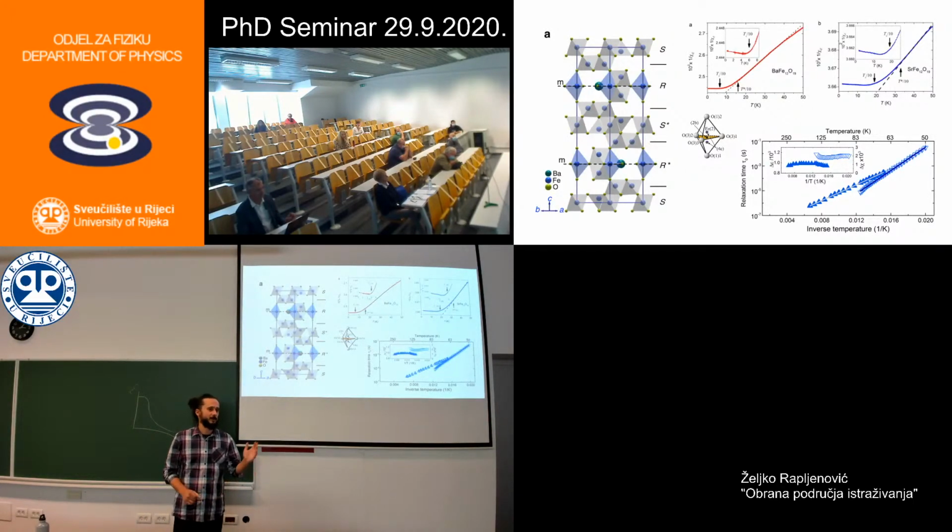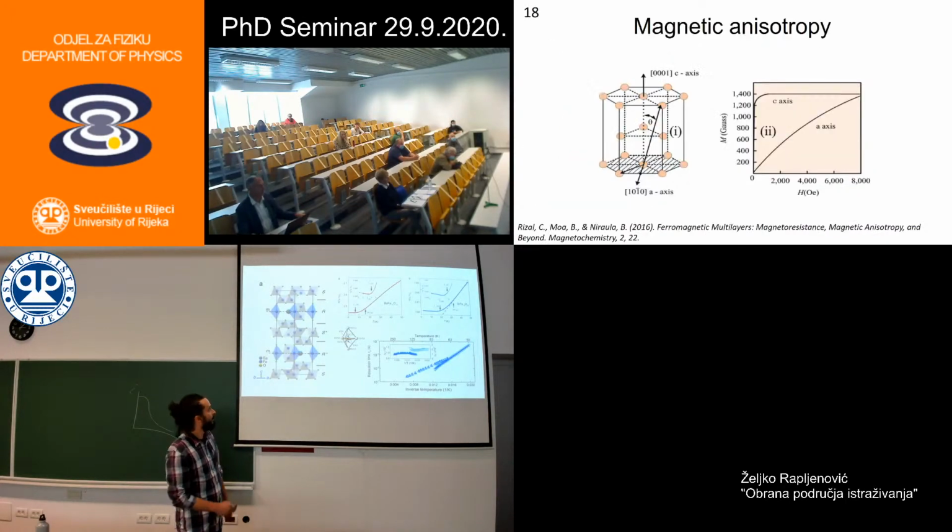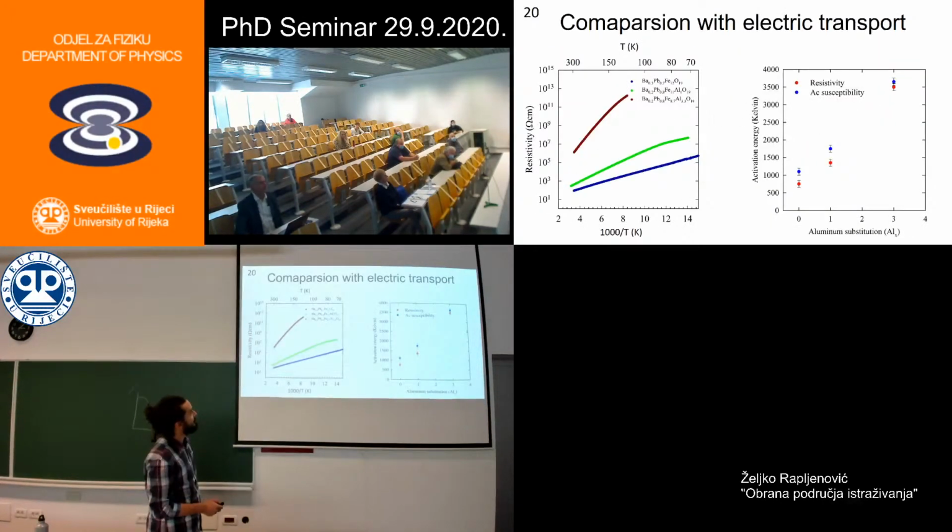So we will try to search for this ferroelectricity. But you didn't mention what the electronic structure of these materials is. What are these materials? They are semiconductors. What kind of gap do they have? It's a very small gap. I didn't mention it, but here is the activation energy, so times 2 is the gap. It's about 1000 Kelvin, which is 0.1 electron volt. So something really small.